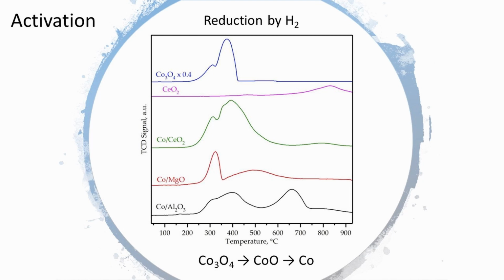In the case of metallic nanoparticles, the hydrogen reduction step converts the metal oxide into metal. More often, hydrogen is used as a reductant. Critical parameters may be the concentration of hydrogen, the pressure, the space velocity and the temperature ramp. A case in point that has been studied extensively is the reduction of cobalt oxide, dispersed on different supports and under